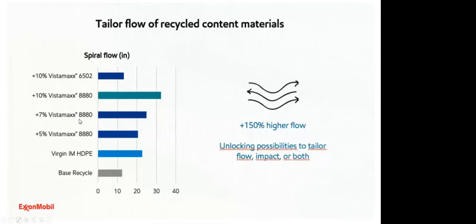So the more Vistamaxx you put in the mix, the higher the flow. And you can see it's a good opportunity to use, for instance, recycled HDPE materials in injection molding applications. It is important to reinforce here that the Vistamaxx application in this case can improve the flow up to 150%.